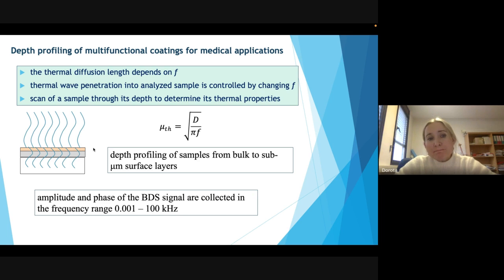We would like to see how the diffusion of drugs occurs in such a system by analyzing the change in the thermal properties of single layers. As I already said at the beginning, we can adjust the depth from which we collect information by changing the modulation frequency of the excitation radiation. So we can scan our sample from the bulk to sub-micrometer surface layers. In the case of these samples, the measurements were performed at relatively high modulation frequency, up to 100 kilohertz.